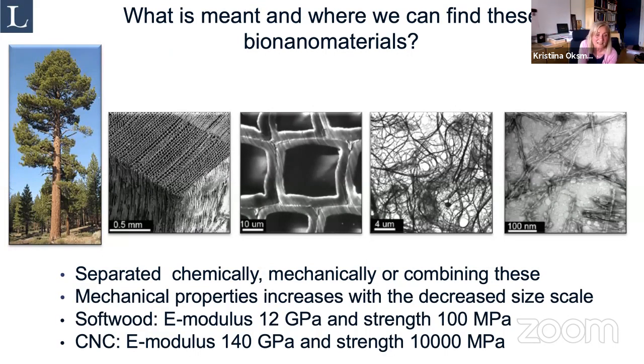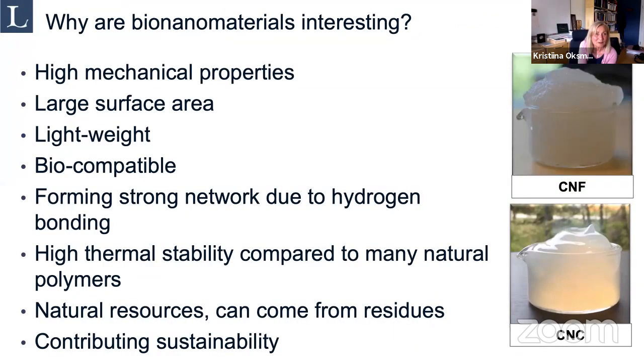I would also like to highlight that the mechanical properties increase with decreasing size. If we take softwood, the modulus is about 12 gigapascal and the strength about 100 megapascal. Then for the smallest part, these crystals, the modulus is about 140 and the strength is about 10,000 megapascal. So the properties improve a lot. And why is there such big interest in these bio-nanomaterials? I have listed some properties which I think are interesting: these high mechanical properties, high surface area, and they are of course lightweight. They are biocompatible, and they form very strong networks due to hydrogen bonding.